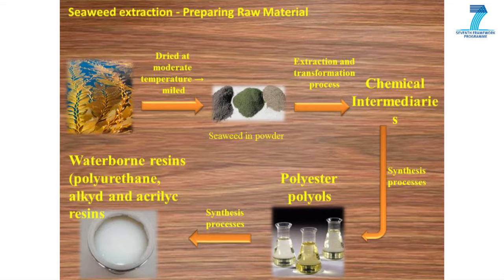Then synthesis followed and the result of synthesis were three types of polyols as target group: polyester polyol, alkyd polyester polyol, and unsaturated polyester polyol. Modifying the monosaccharides with fatty acids of long chain can be applied especially in the synthesis of alkyd polyester. By esterification of one or more OH groups in the monosaccharides with acrylic compounds can be specially applied in the synthesis of unsaturated polyester polyol. Moreover, the acid and sulfonic groups have ionic character themselves and can be used as dispersible groups to include into polymers' backbone.